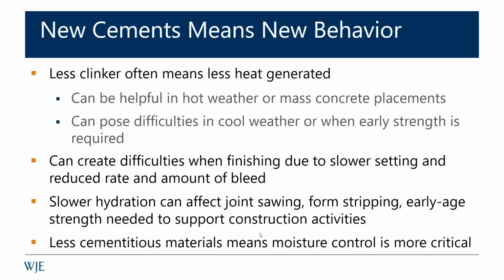And then less cementitious materials. This I think is really important. As we cut back on the amount of cement we put in our mix, we have to control our moisture much more tightly. Often we have these really high cementitious content mixes because the ready mix producers have fluctuation, either wash water left in the trucks, or not monitoring and responding to changes in moisture content in their ag stockpiles, and those fluctuations in moisture at lower cementitious contents have a dramatic impact on the water cement ratio and therefore a dramatic impact on strength. So as a hedge, it's easy for the concrete producers to put another 50 pounds, 80 pounds of cementitious in just to help give them more assurance on achieving strength.